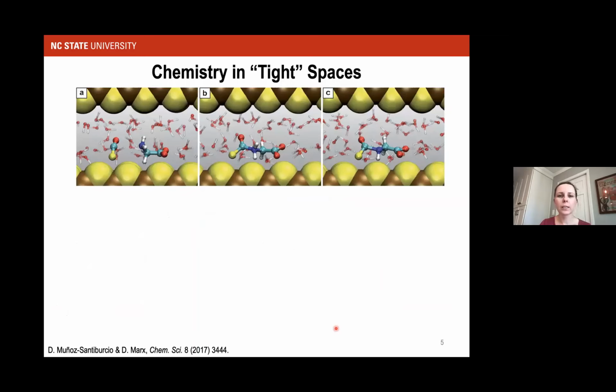So I wanted to give you a little bit of an overview of how I got interested in this particular research space. There's a series of papers from the group of Dominic Marks on chemistry under confinement, or chemistry occurring in very, very tight spaces. And what's illustrated here is the top and bottom surfaces are a layered material, an iron sulfide layered material that is separated by some interlayer spacing, where that interlayer spacing allows for water as well as organic molecules to be present. And these three different panels are representing a chemical reaction that's occurring in this essentially nano-confined environment formed between the layers of the material.